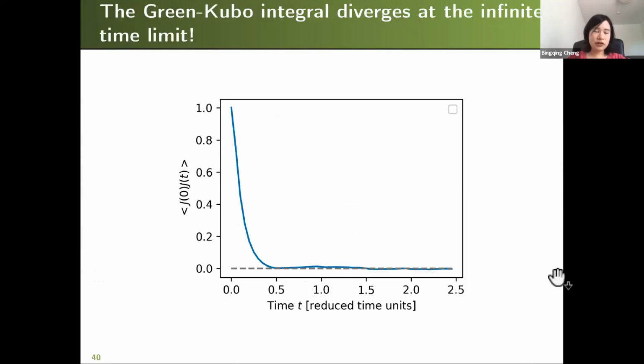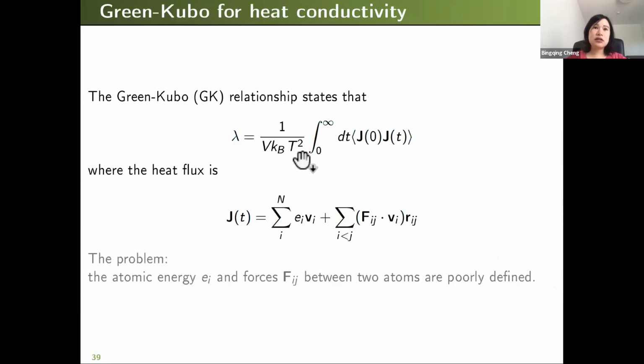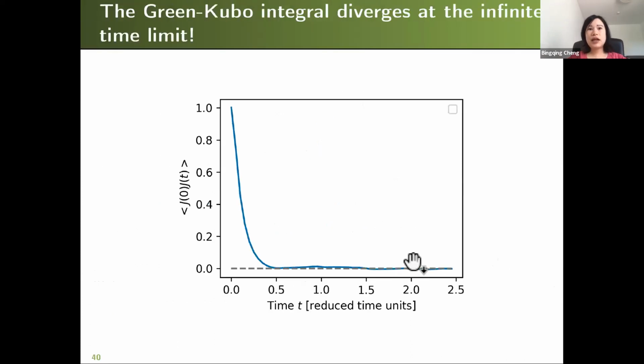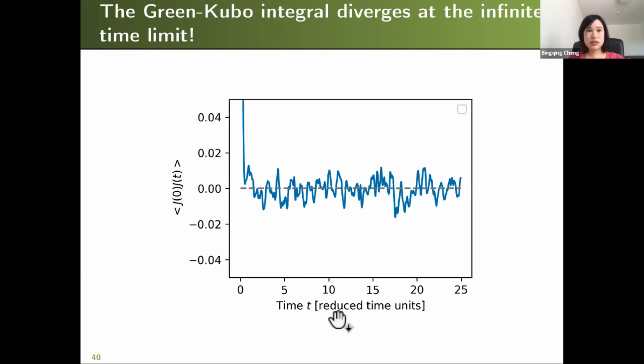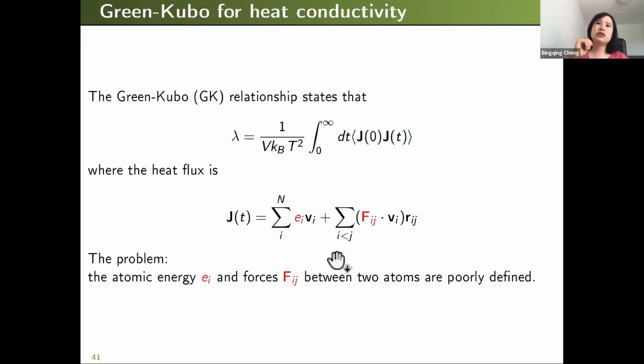And this is actually a little bit problematic because notice that this integration goes from time equal to 0 to time equal to infinity. But if we have the autocorrelation function computed from our simulations, inevitably this comes with a little bit of noise. Right. So if you actually integrate to the infinity, you will have a divergent estimate. So that's not feasible. So in practice, people usually cut off somewhere. But that, of course, introduces a systematic bias because the autocorrelation function can have a long decaying tail.